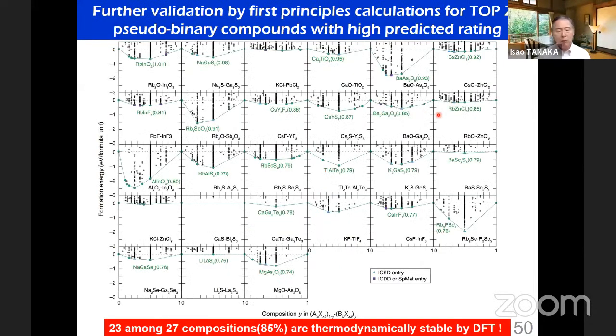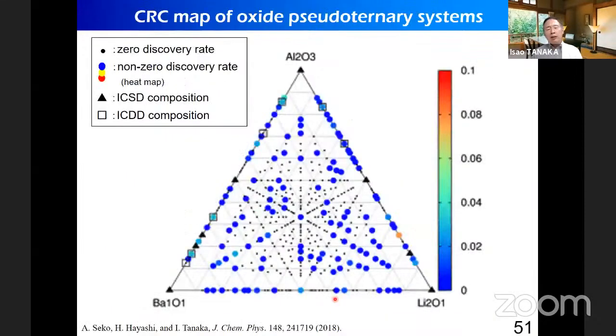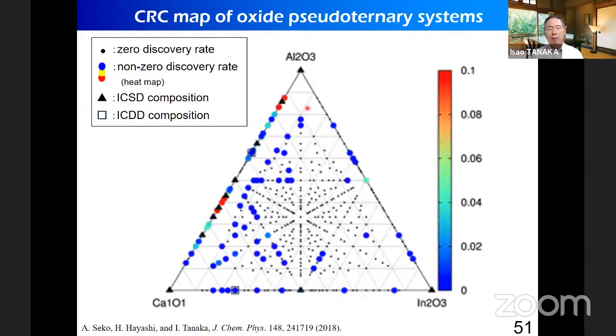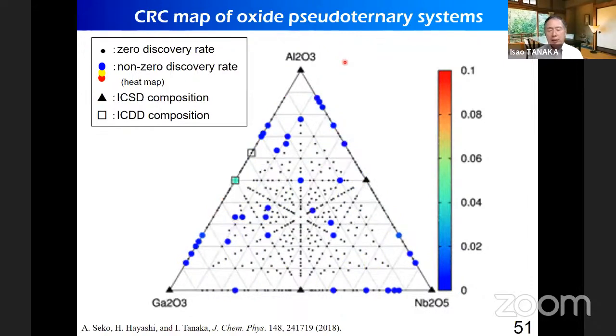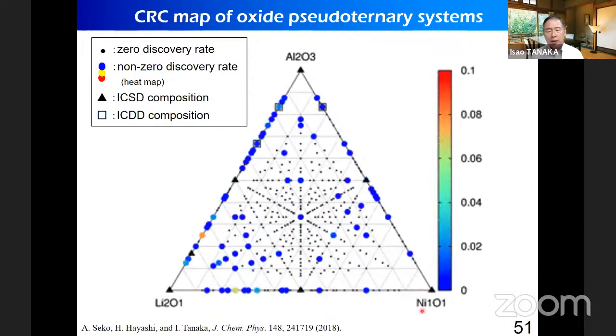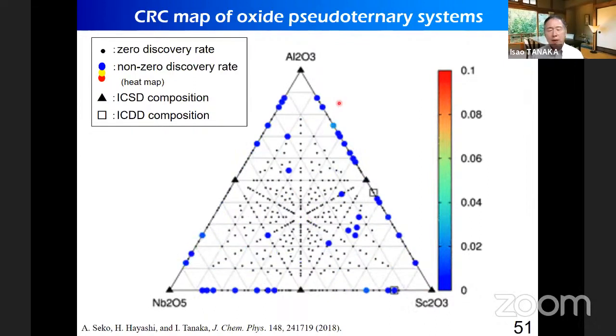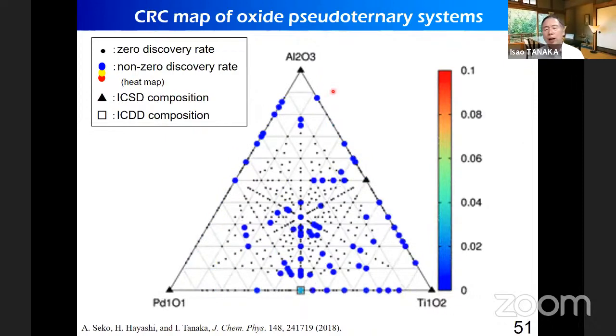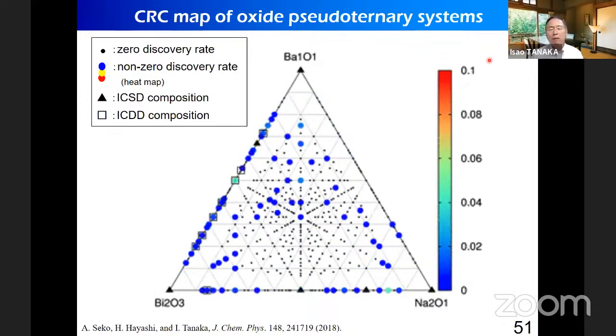Similar calculations were done for 27 different pseudo-binary systems, and the success rate was 85% within the DFT calculation. So this is quite a satisfactory result, we believe. So in that way, we can make this type of map. And you can see that the end member is changing all the time. And at certain points, you can find some red marks, which show high probability to find a new compound.